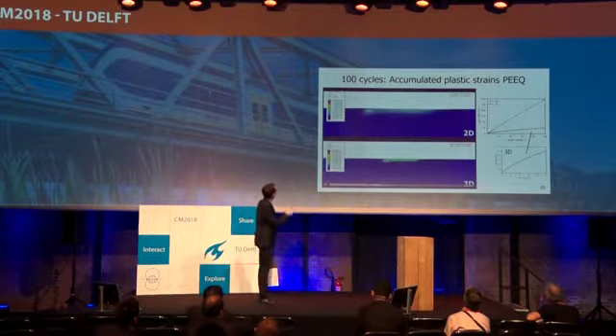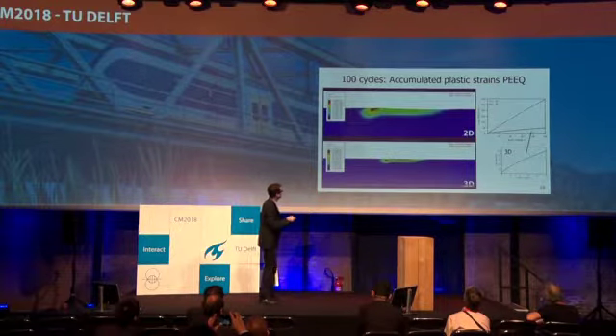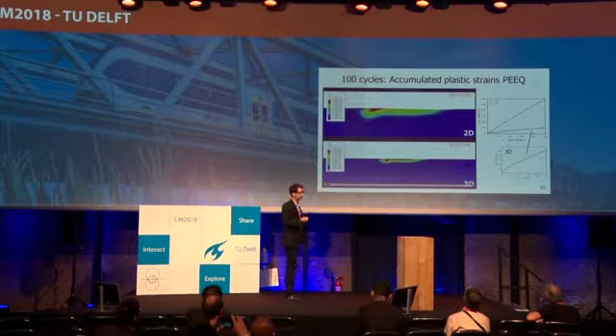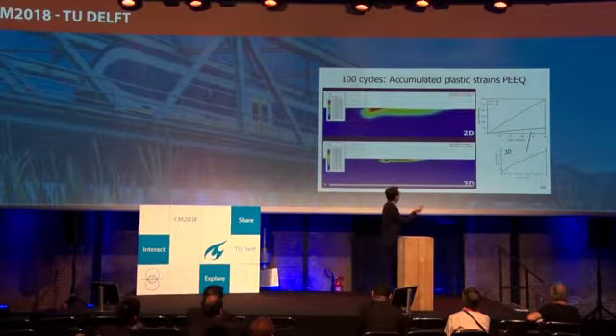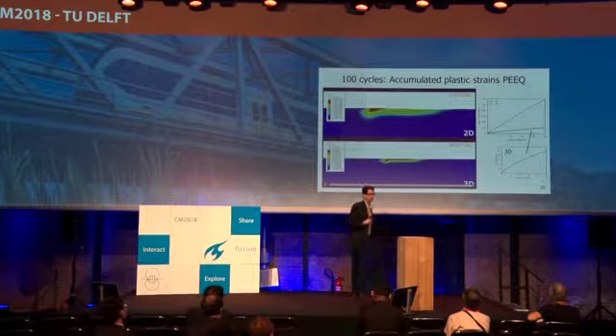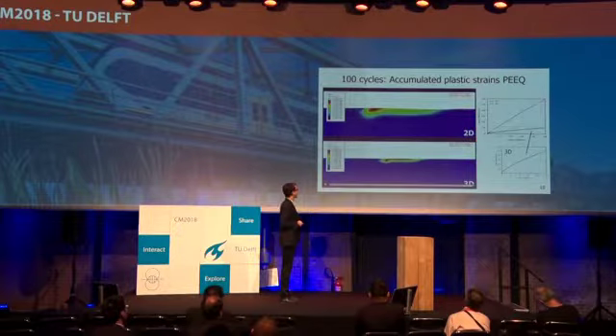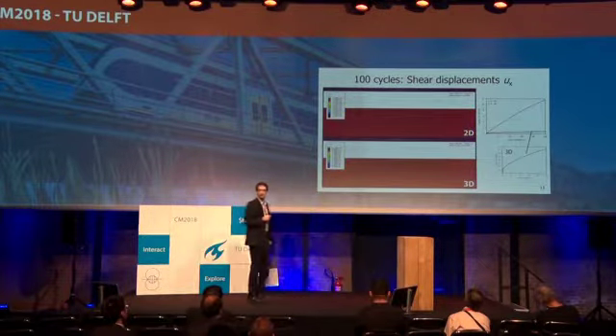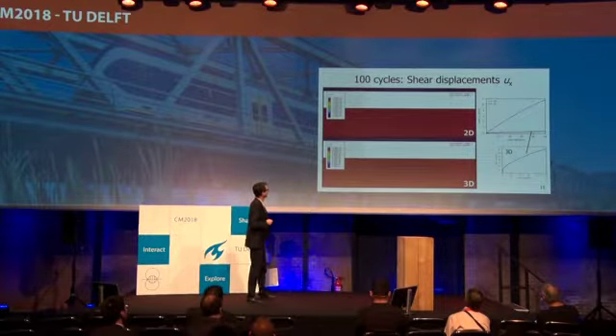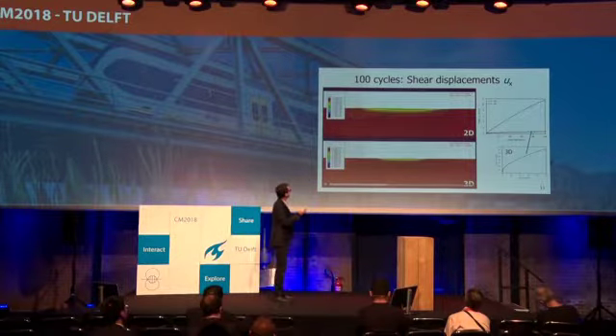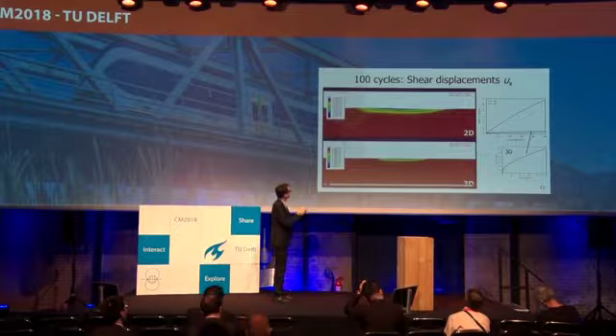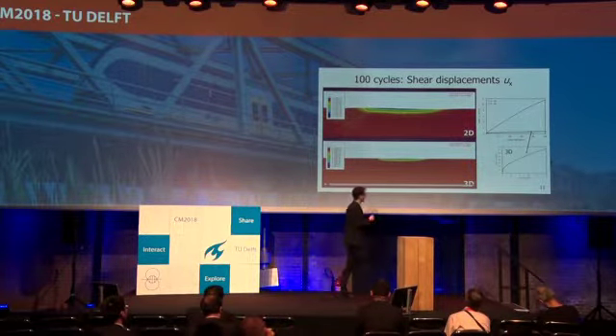Thank you. And we see the accumulated plastic equivalent strain in the 2D model and the 3D model. The legends here are different so that we see something, because, as we can see here on the right, the PEEQ values are much bigger in the 2D case than the 3D case. Of course, it's a lot less resistance to shear displacement when you have a 2D model compared to a 3D model. And also the deformation depth is completely different. But the thing that interested us the most is the shear displacement that we can see here. If it's possible, please also run the video. Again, different limits, and we see how we get the shear displacement and how not uniform this is. We have some effects here, we have some effects here, and in the 3D case, it's a lot more uniform, and also the depth is a lot less.